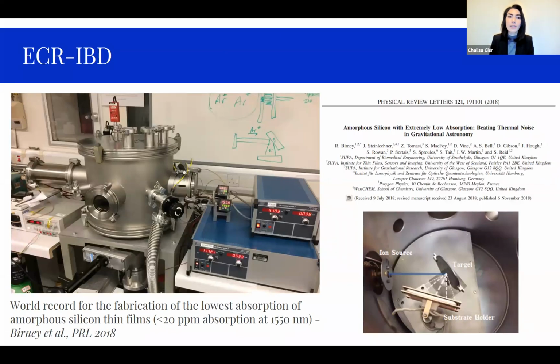Currently, we have 3 ECR ion beam deposition systems at Strathclyde, and this is the prototype system with only one ion source. This system has actually demonstrated the lowest optical absorption ever reported in amorphous silicon thin film. You can also find this paper in PRL journal, published in 2018 as well.